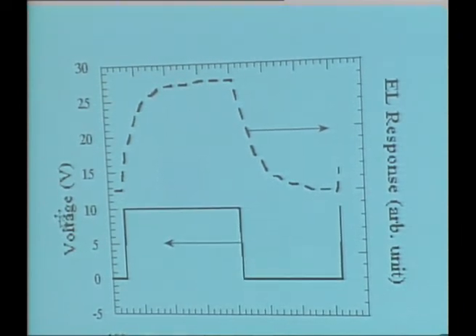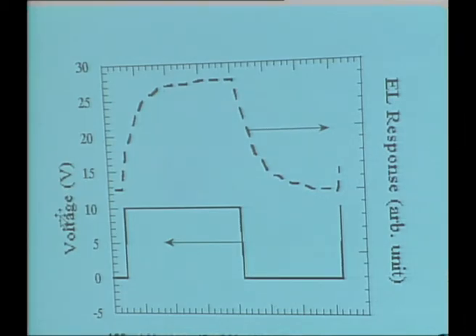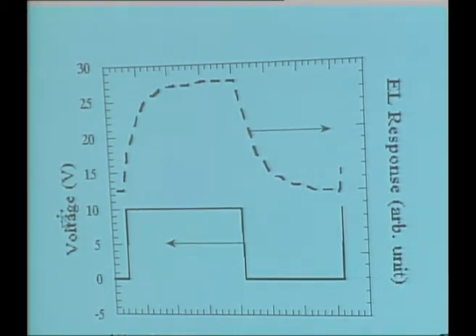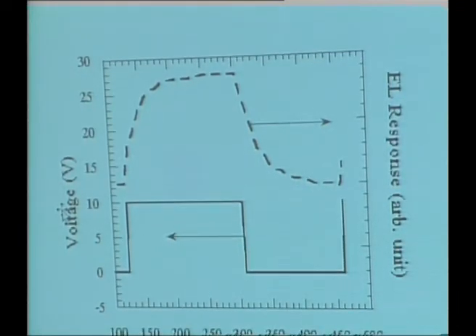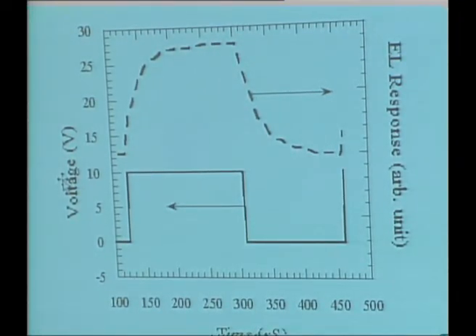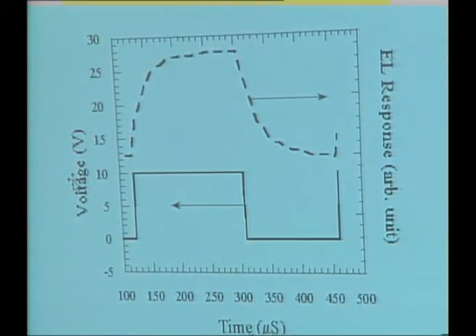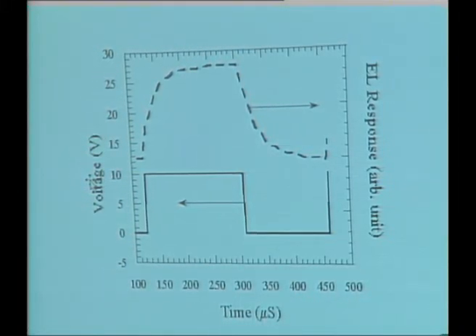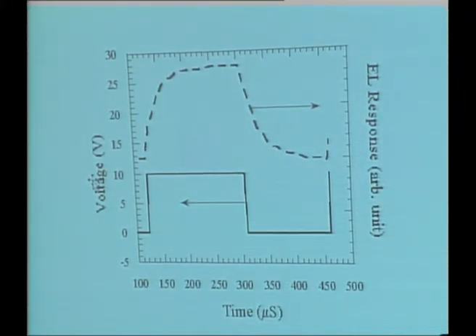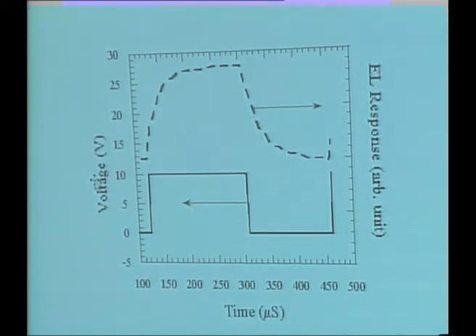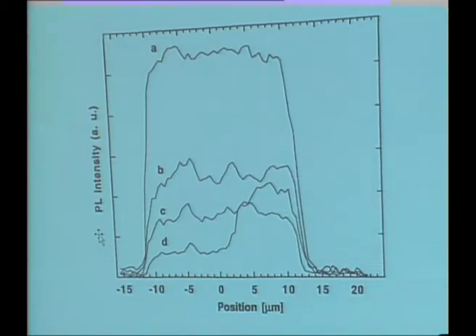In the frozen junction regime, you can get fast time constants because ions do not move. So the time response of the turn on of the light is just like in an LED, where it's only electronics. So this is an RC time constant decay. It has nothing to do with the ions. One is getting 20,000 candelas per square meter at 5 volts in spite of the fact that there's some heavy quenching here.